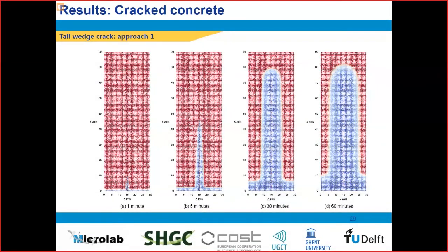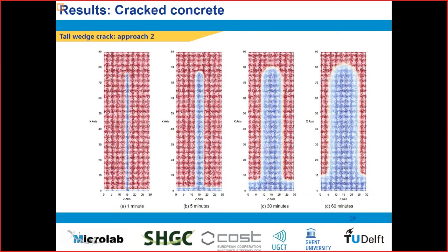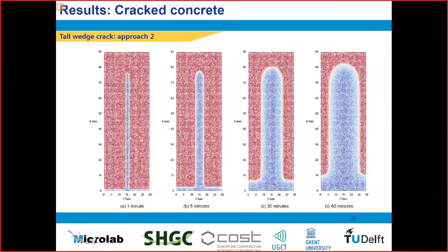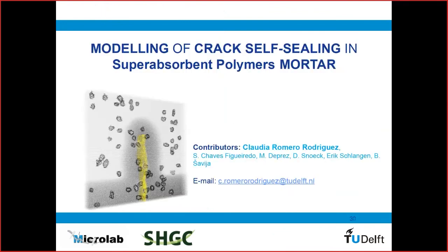So you can see in approach 1, this goes quite slow, which is not representative of what really happens in the crack. And in approach 2, immediately the crack is filled to a certain point, and then it keeps going. And you can see that there are differences even in the long term after 60 minutes of water penetration. So you have more water penetration where, of course, you have the crack filled right away, which is what physically happens in this case. Okay, so this is the first part of my presentation.